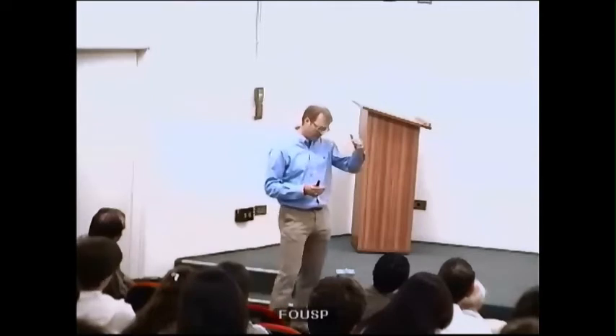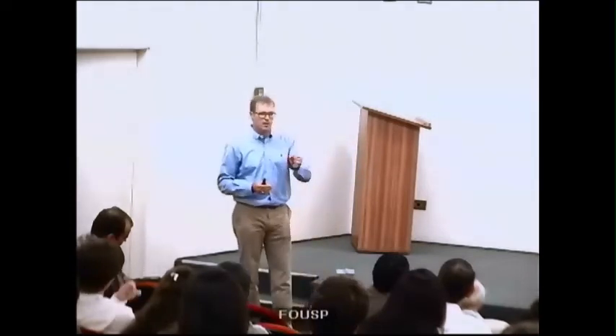Yeah, that's right. What I wanted to say with hybrid materials, let's say if you have a filler size of 0.5 micron, 1 micron, 1.5 micron, there is a critical size of a defect which releases a crack to grow at a certain stress. And 1 micron, 1.5 microns are still far below the critical sizes for this kind of materials. If you have a particle which is 20 microns in size and irregularly shaped at the surface, this could influence the strength, in terms of a big particle reducing the strength. But these particles are all below the critical sizes for the fracture releasing influence.